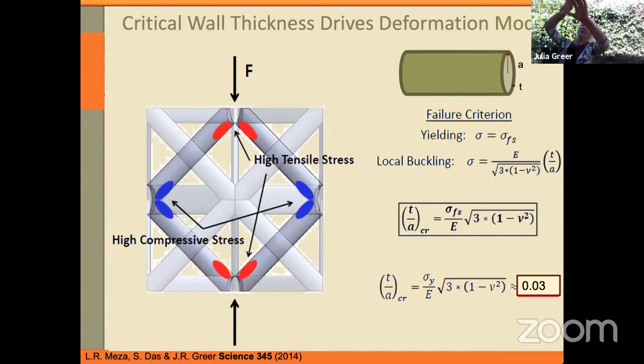So if you just make a very simple model, and you can see this beam, the wall thickness is T, and then the radius is A, you can set the failure criterion. The local buckling would occur at something where the critical figure of merit is this T over A ratio, and then the yielding in this case would certainly be failure since it's a brittle material. So setting them equal to one another, for this particular material, alumina, we can come up with the critical fraction here. So this T over A critical for this material is about 0.03.